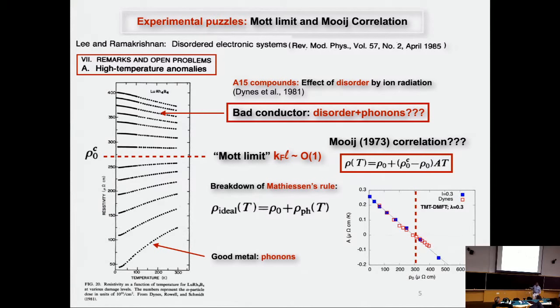Well, the first reaction is that the temperature dependence comes from phonons. We know this very well. And then the slope changes sign. So it has something to do with phonons, and it has something to do with disorder. These kinds of systems where this is seen are not strongly correlated materials of the Mott type. This is far from the Mott transition. Probably electron-electron interactions are not very important here. And there are broad classes of materials in this class.